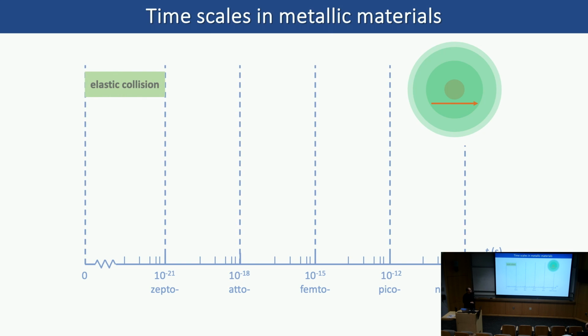Okay, so in terms of time scale, the first thing that a high energy electron could do is to transfer energy and momentum to a nucleus, and that's what we call elastic collision. And the elastic collision happens in what is called 1 zeptosecond. I don't know how many of you know this scale, it is 10 to the minus 21. So it's a very fast process. There are also what we call inelastic collision, where the high energy electron could transfer some energy to the electrons in the crystal so that it could excite the material. And that inelastic collision happens on the order of attosecond. Once the material goes to the excited state, it takes about femtosecond for a metallic material to get back to its ground state. So that's a time scale.